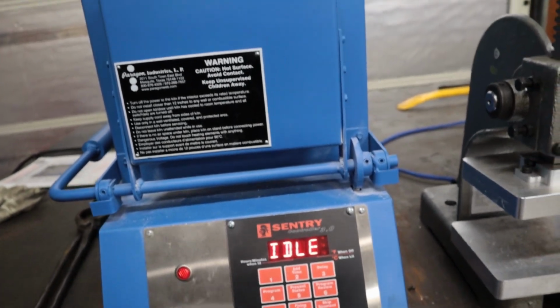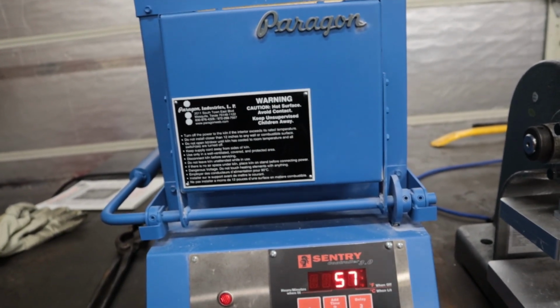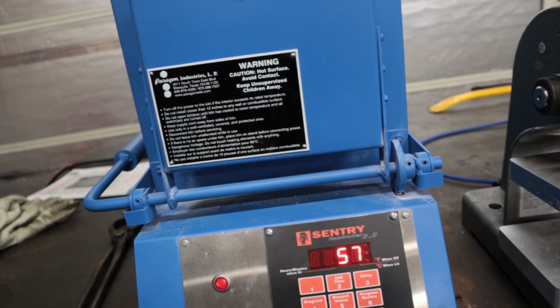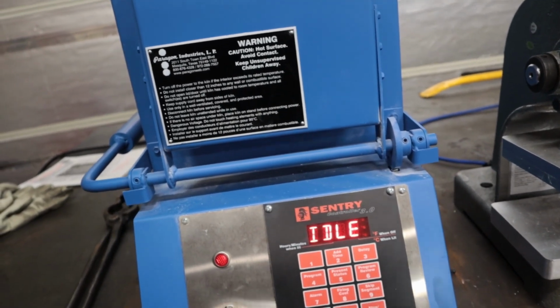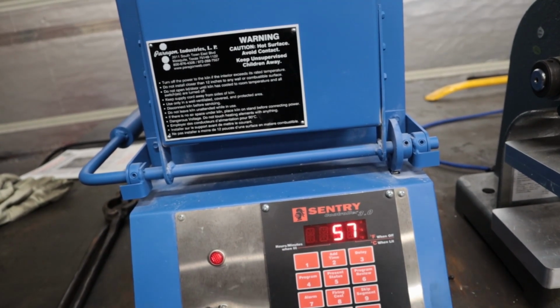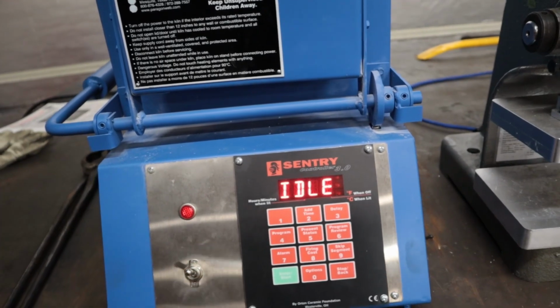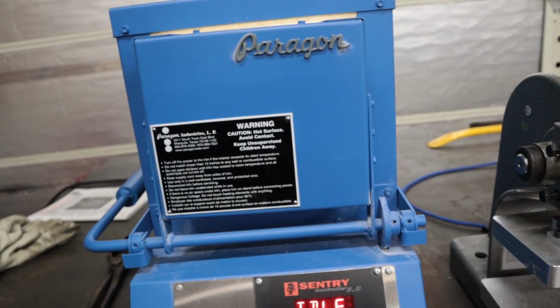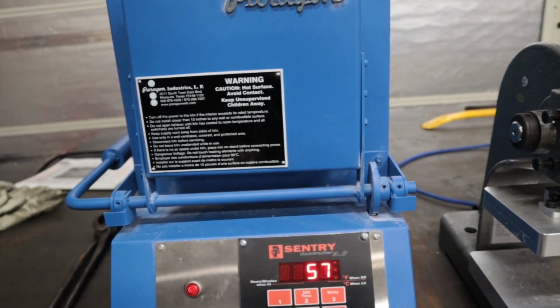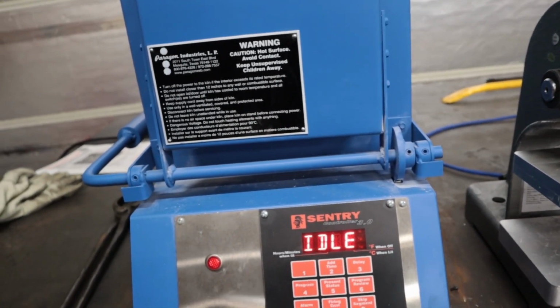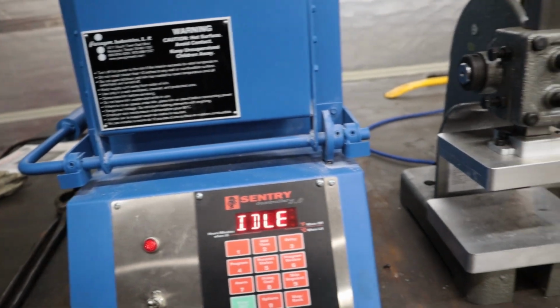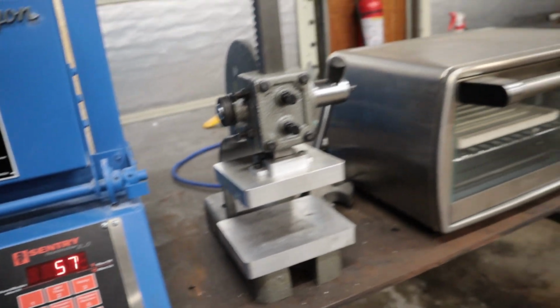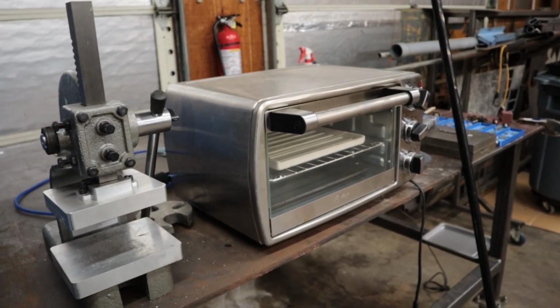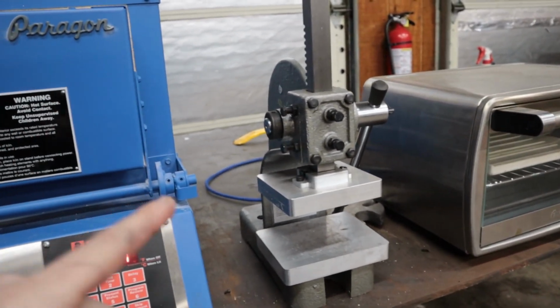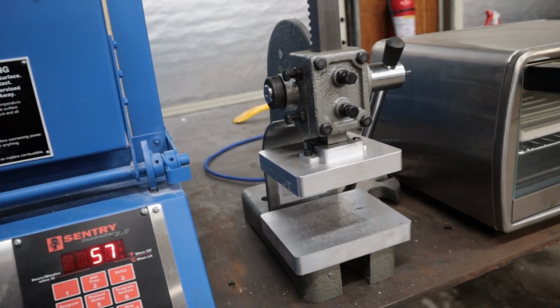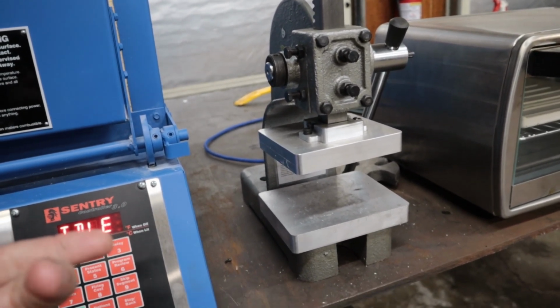So this is a Paragon heat treating furnace. It's brand new. I've only used it like 20 times now for these new blades, and it was not cheap whatsoever. So for the blades, I'm going to, what is it? Because I'm not doing cryo right now. 2050 is the temperature I'm going to, with a plate quench, and then 400 degrees tempering, and I'm holding it on the plate for 15 seconds for a first blade.